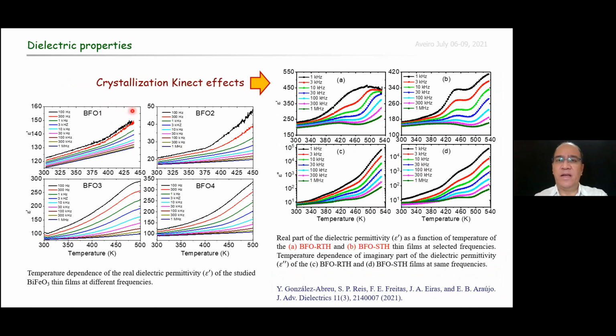Moving to the next, we can see that the crystallization kinetic effects, such as rapid thermal annealing and slow thermal annealing, change the shape of the curves, but the peaks remain, as observed in these figures. It is an important result because it suggests that we need to control the defects during the synthesis. If a BFO film has a specific defect, such as oxygen vacancies, bismuth vacancies, or interfacial defects, we can see from this result that it is practically impossible to remove these defects after the synthesis.